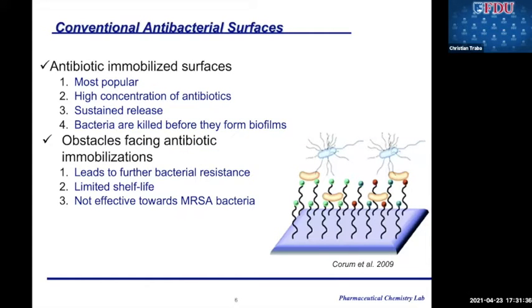Until recently, antibiotic immobilized surfaces were considered the most popular surface modification technique. In this technique, a high concentration of antibiotics are introduced onto a surface, and the antibacterial activity stems from a sustained release. Consequently, the bacteria are killed before they form biofilms.